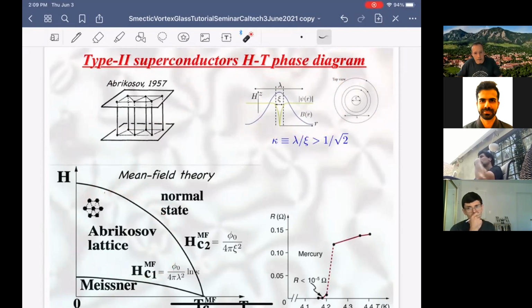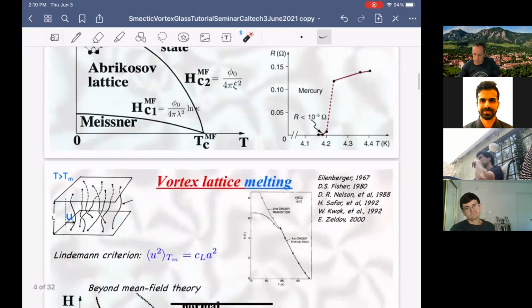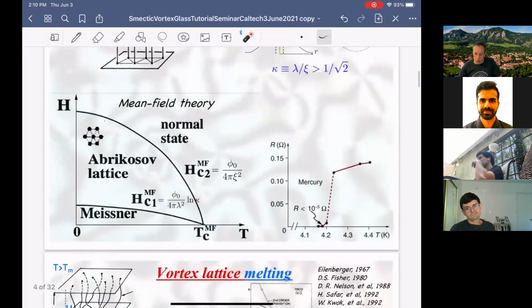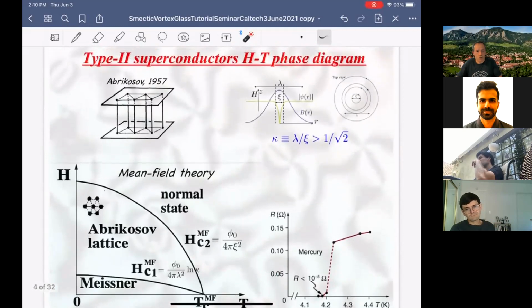And so the two critical fields, Hc1 and Hc2: the lower one is the flux quantum per London penetration length squared, give or take, and Hc2 physically is the scale of the applied field, a scale of flux density, when vortices begin to overlap. So then the flux density is one flux quantum per coherence area. But this was the picture that existed since 1957.